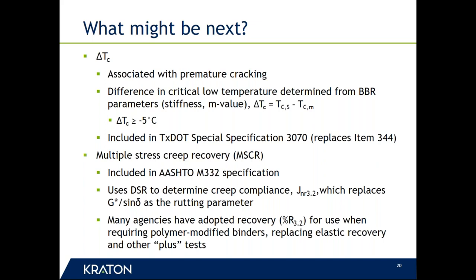That difference in critical temperature has been associated with premature cracking. And so what they're trying to do is to limit that difference, in particular where the relaxation controls, to a given amount so that you don't have that issue come up.